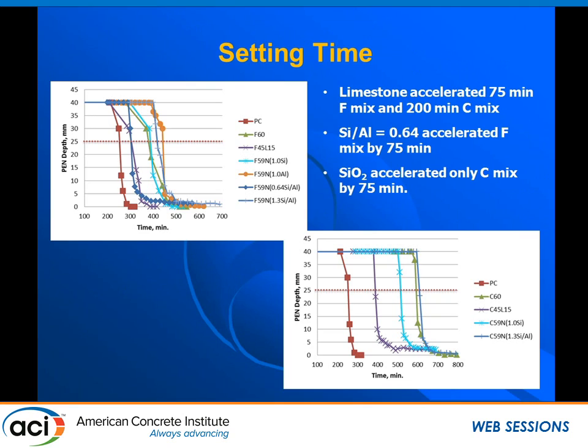Let's have a look at the setting. Here in red is our PC mix. The green, in both cases, it doesn't look very green, but the greens are the fly ash and cement only. Then we have the 15% limestone in blue, and we see we accelerate quite a lot in both fly ash C and fly ash mixes.